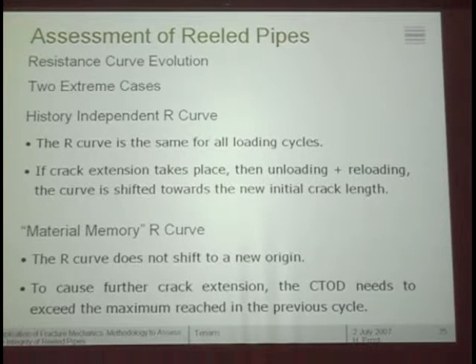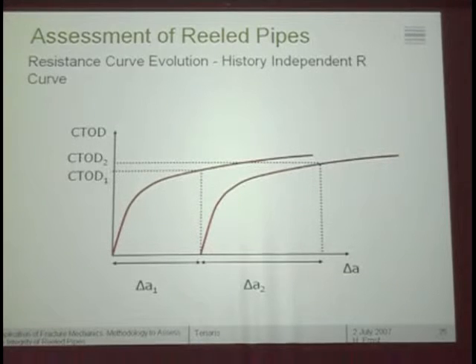And that is more or less the opposite. That is, the R curve does not shift to the new origin. So if you have one cycle, you have some growth, you come down in load, and you will have more extension only if you exceed with the CTOD the previously reached value. If you do, then you will have some crack extension, but that crack extension is given by the resistance curve itself, a point at the very first origin. I'm trying to show you this now.